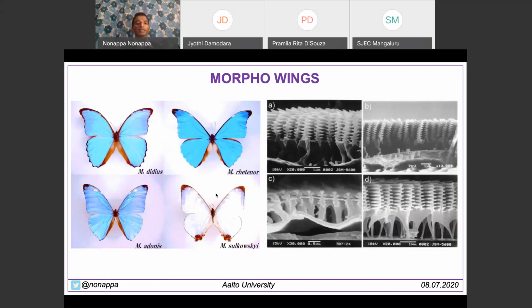And if you look at the high resolution electron microscopy of this cross section of the wings, what you see is that they have some specific pattern, this kind of alternate pattern, and these alternate patterns are not having two different materials. Instead, what they have is the air cavity. And that is why you can have a very broad angle vision of color for morpho butterflies. And the only difference here is the size and the number of these grated layers. It is as simple as that.